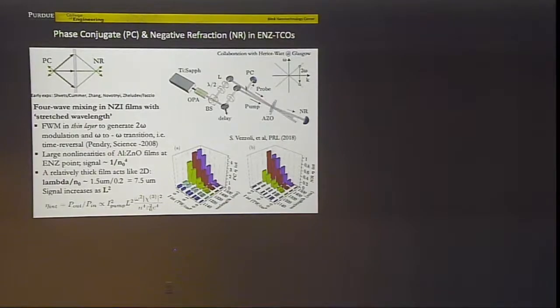So what we obtain is actually 100% conversion efficiency. It could go even beyond 100%. You shouldn't be surprised by this because you take energy from the pump. So the point here is that this low index enhanced nonlinear optics is pretty much a new branch in nonlinear optics, and it's true for many optical processes. But we took it to yet another level.